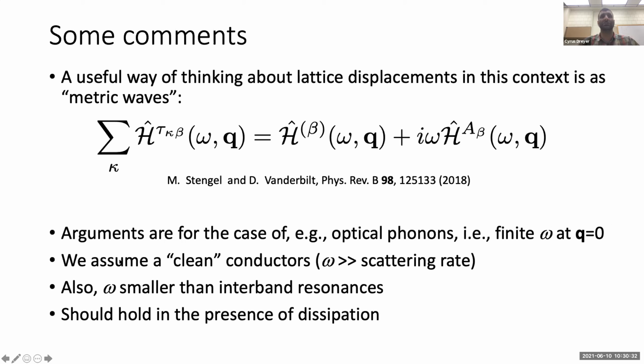Also, we assume, in quotes, clean conductors, meaning that the frequencies we're considering are much larger than the scattering rates. If we have a dirty conductor where this criterion isn't fulfilled, then we would expect the electrons, by scattering, to relax down to their equilibrium positions and the non-adiabatic Born effective charges to vanish.